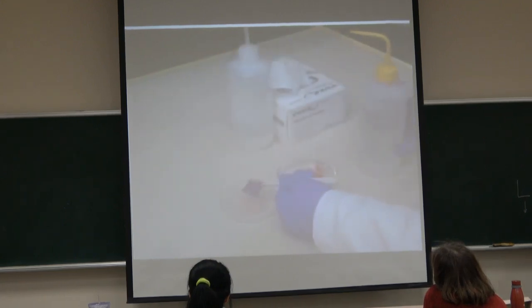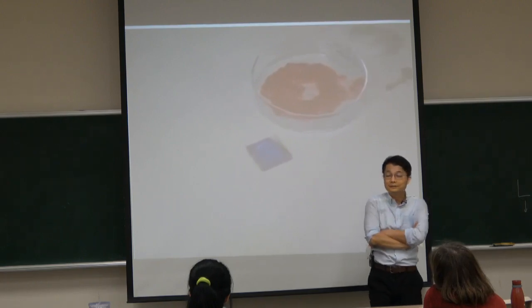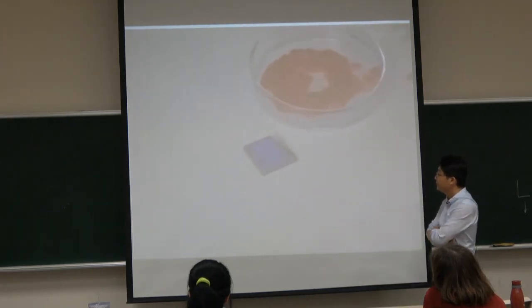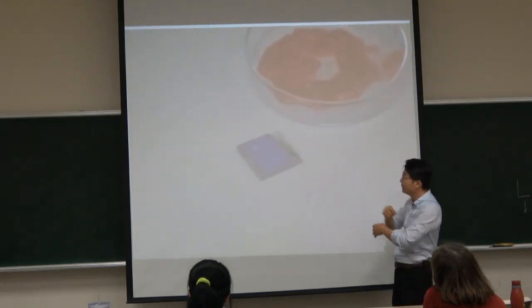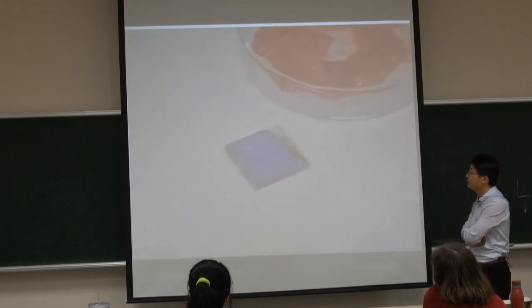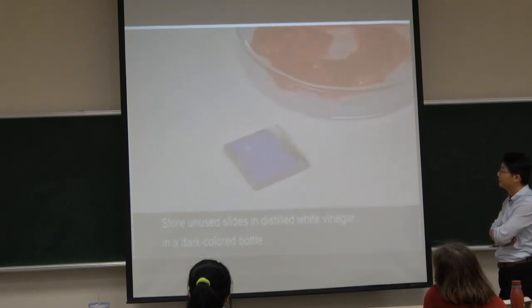Step 5. Lift the slide out of the juice using a pair of plastic tweezers. Rinse the slide first in distilled water to remove any fibrous debris from the berries, and then in ethanol to remove excess water from the porous titanium dioxide coated section. Blot the slide dry with a soft tissue. You can use the ethanol. Step 6. You have now made a titanium dioxide dye-sensitized electrode. If the slide is not going to be used right away, store it submerged in distilled white vinegar in a closed, dark-colored bottle.